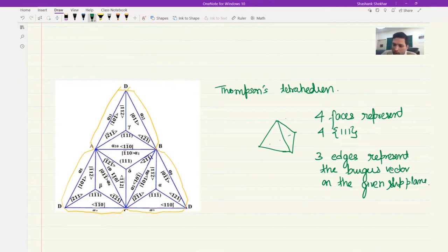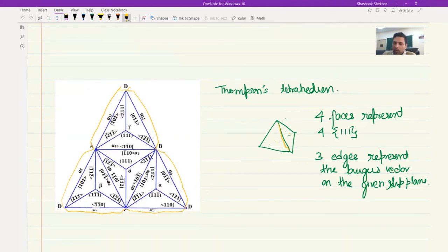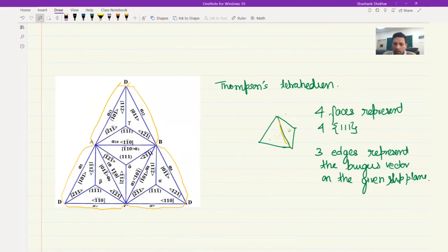Clearly from this, if you take a particular edge which is shared between two planes, then that particular Burgers vector is common to both of those planes. It also tells you a lot about dislocations. So if you have a screw dislocation with this Burgers vector, the screw dislocation line vector is also along this direction, and therefore it can cross slip into either of those planes. So this is giving you information about the slip plane, the slip direction, and also what are the possible cross slips in the FCC system.